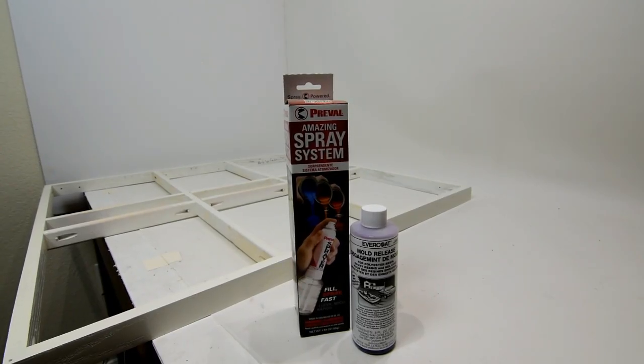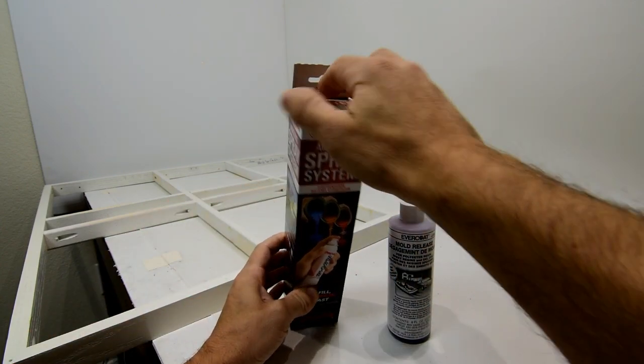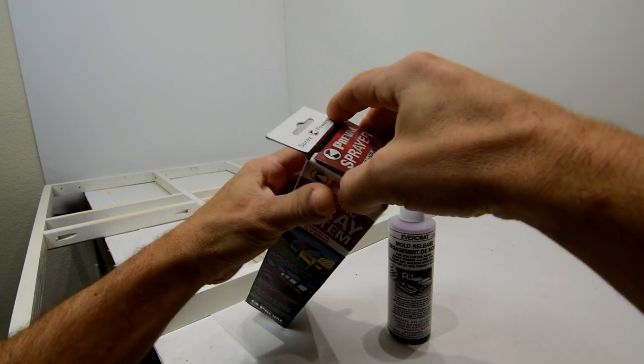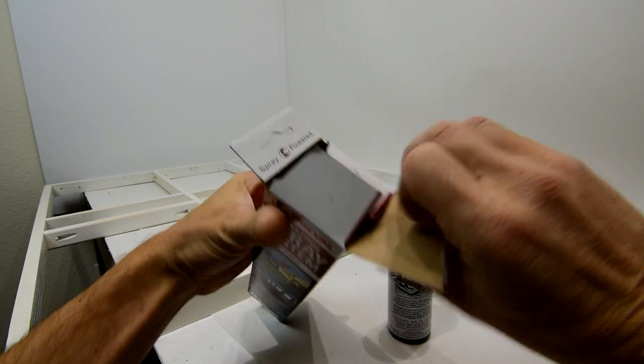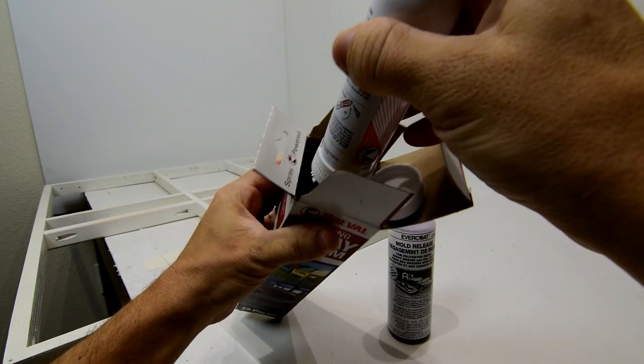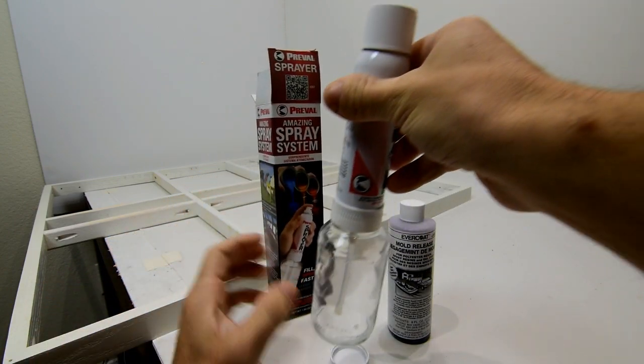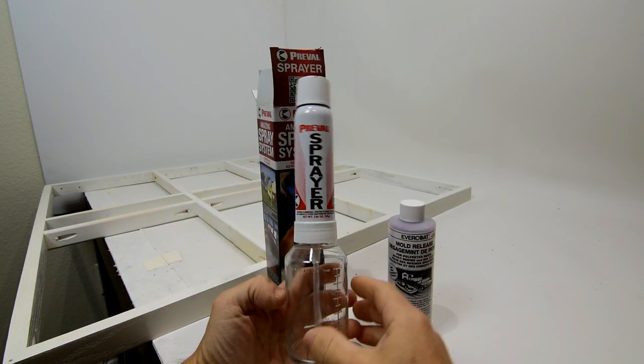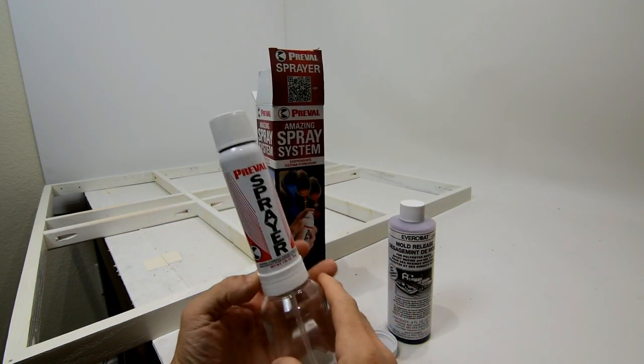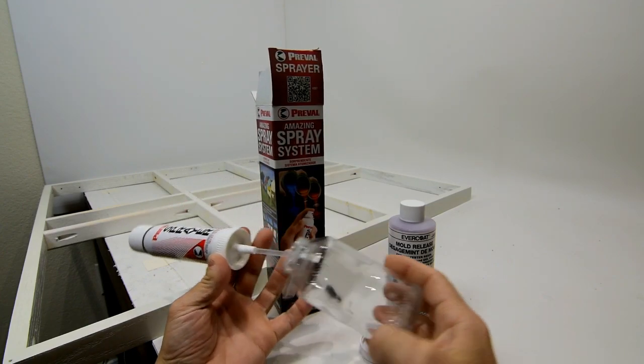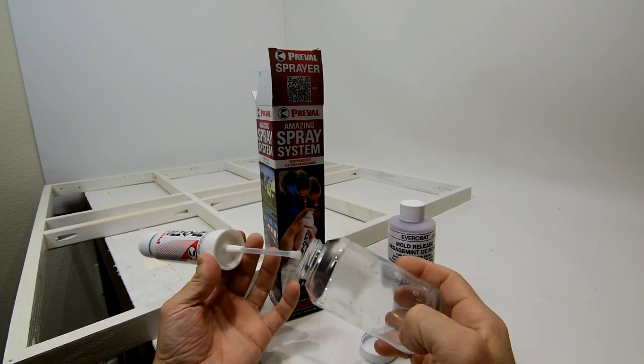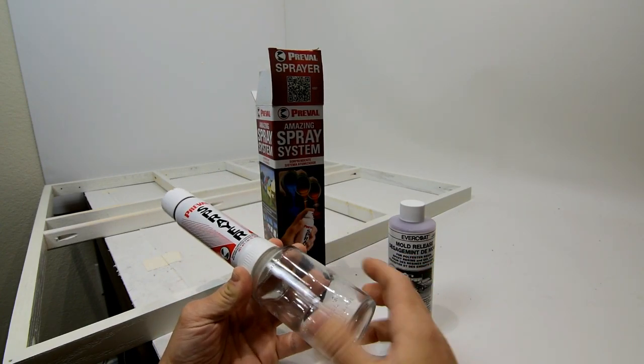PVA is a water-soluble mold release agent and you spray it, or I spray it using one of these little Preval sprayers you can buy at Lowe's. They're about seven to twelve dollars and it allows you to take pretty much any liquid and turn it into an aerosol spray can. So I pour the mold release agent here, spray it, and it creates basically like a plastic film that's removable. So when you delaminate the carbon fiber from the mold it all comes off nice and easy.